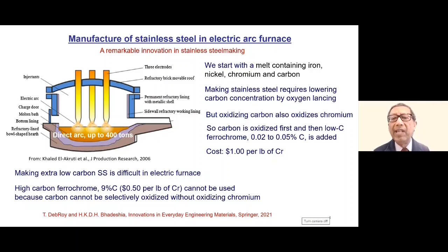But the problem here that one encounters is that when we try to oxidize carbon, we also oxidize chromium. So in order to avoid the oxidation of chromium, we first of all oxidize carbon, lower the carbon content to our desired level, and then add ferrochrome.